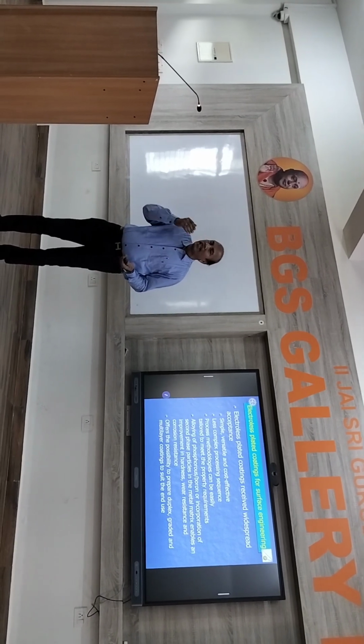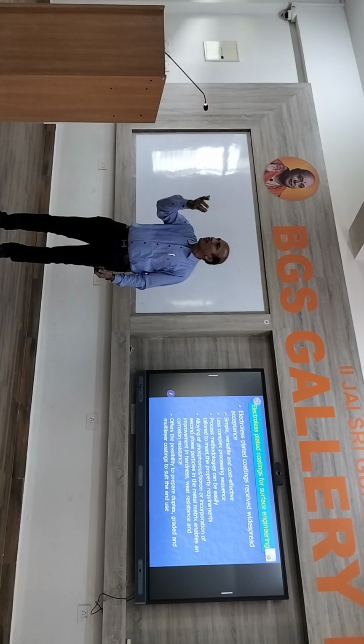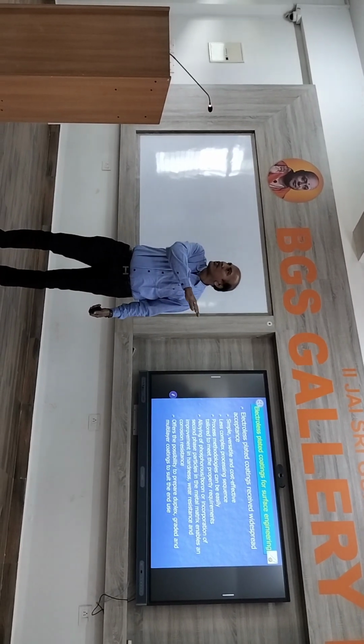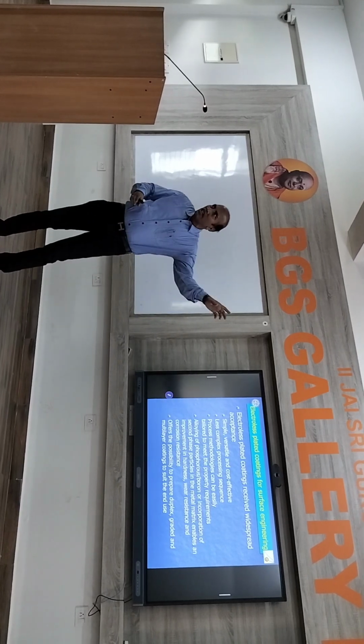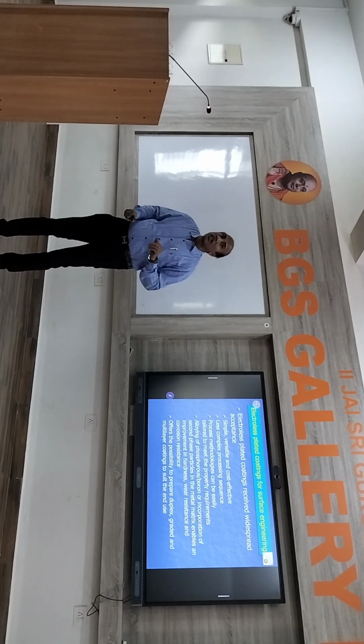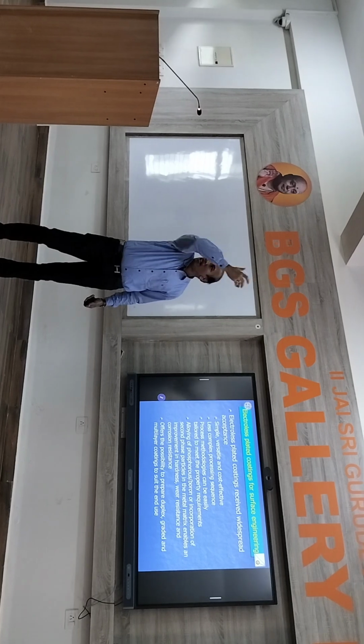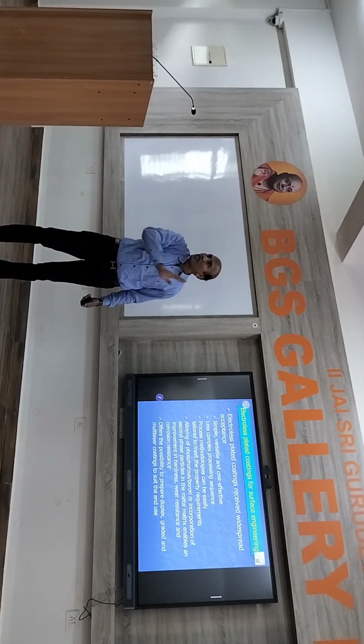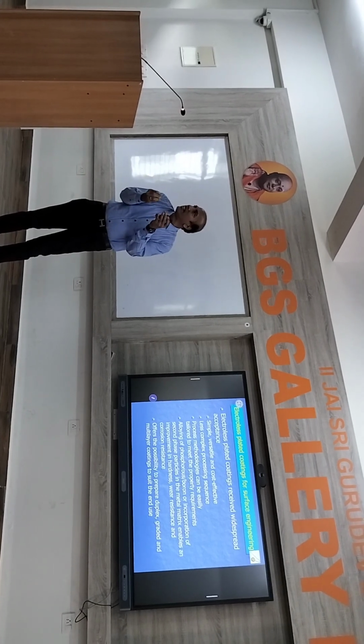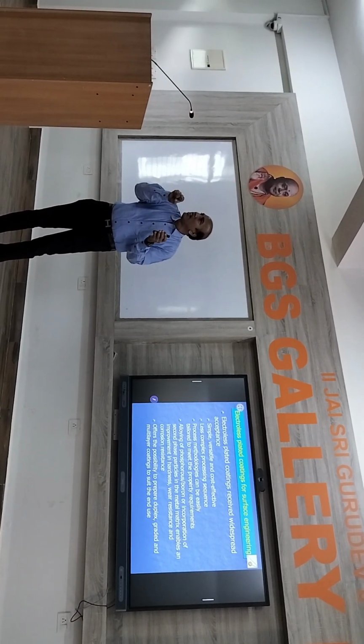For example, high reflectivity, which we have worked on for a metallic mirror. We have developed it for two series of satellites. I will give you much more details on that. There, high reflectance is required for that metallic mirror. Whatever sunlight falls on that mirror should be reflected back, 99% should be reflected back, so that the detector kept inside is always maintained at the required temperature. That is one big advantage.